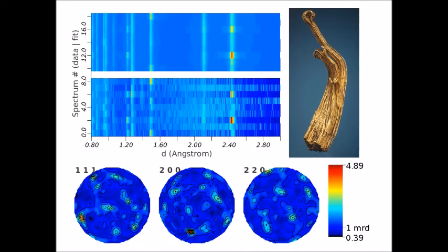Very surprisingly, however, the diffraction data from the wire golds look very different than from the wire silver. We see individual diffraction spots in red and yellow here, and this suggests that although the exterior texture and morphology of these look very similar to the wire silvers, the interior texture is much more like a single crystal or a few large crystals rather than being made up of many hundreds or thousands of small crystals, as are the silver wires.